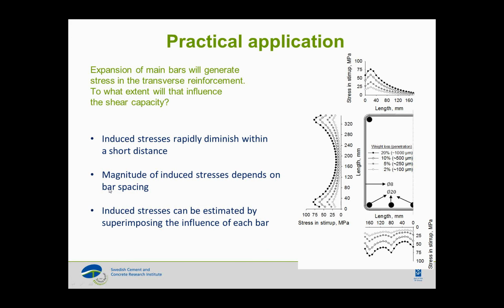But it's also important to realize that maybe you get quite high stresses on the stirrups. In this case, it's about 80 megapascal, but as soon as you go away from the location of the main bar, then these stresses really go down nearly to zero. So they rapidly diminish within a short distance when you go away from the corroded main bar. And that is important to know, because then you only have concern about the case where a shear crack crosses right at the bend of the reinforcement where you have the highest stresses.